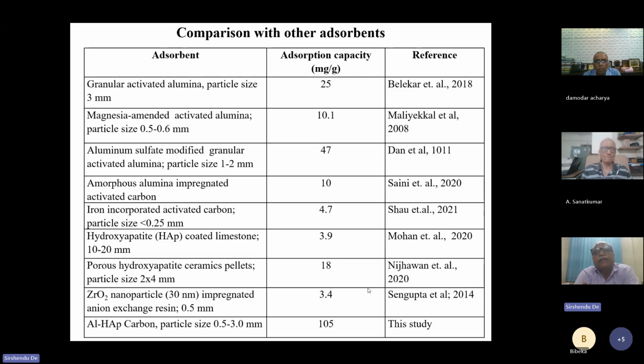I have given a comparison with other adsorbents. If you look into the powder-based adsorbents, their capacity is always higher. But powdery adsorbents, micron size or nanometer size, cannot be used as a filter media because of the high pressure drop and leaching of the medium. Therefore, we compared this with the granular media, and we have found that among all the granular media, we have obtained the highest ever reported value, 105 milligram per gram, which has a particle size of 0.5 to 3 millimeter. This is an ideal medium size for preparation of a fixed bed adsorption reactor.